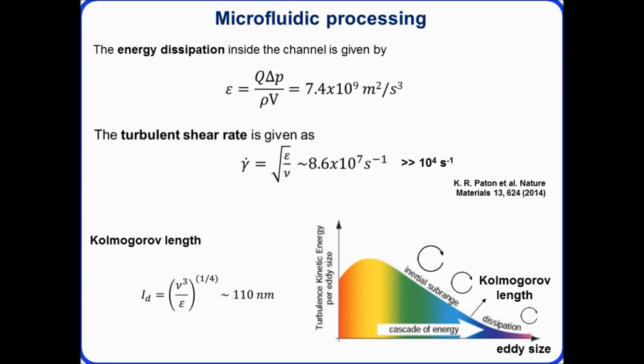Another characteristic which defines a turbulent regime is the Kolmogorov length scale. In a water-based system, what we have is the energy dissipating through different eddy sizes until you get down to this regime, the viscous subrange, which is determined by a length scale on the order of 110 nanometers. So we think this might be a key parameter in controlling the size of the graphene flakes that we can produce. If we change the viscosity of the system, we might be able to tune this length scale to, for example, increase the size of the graphene that we produce.